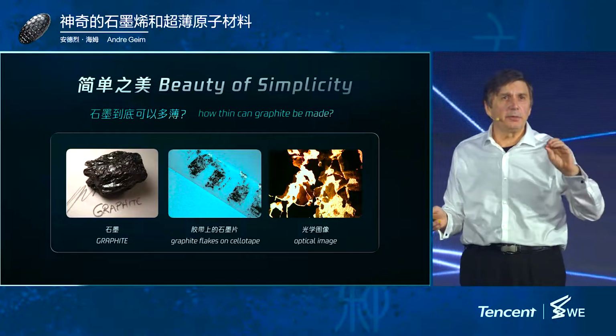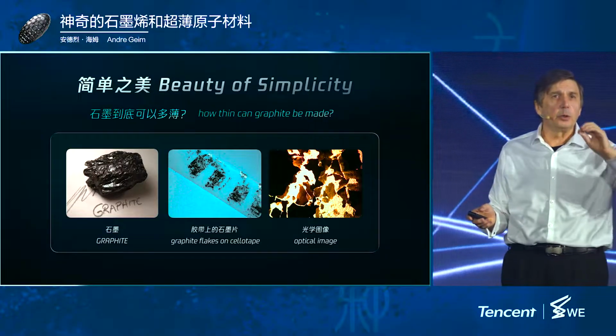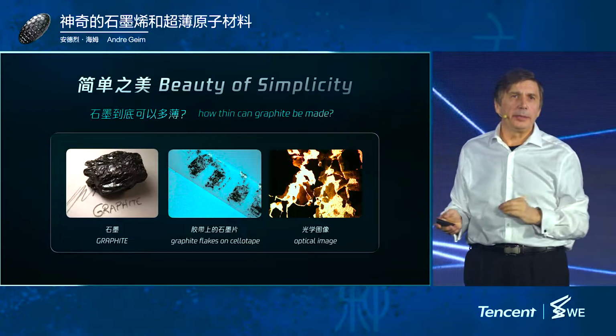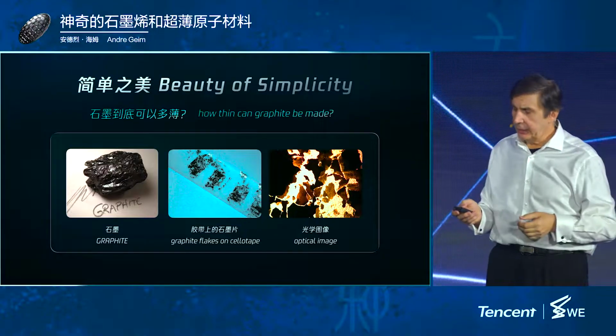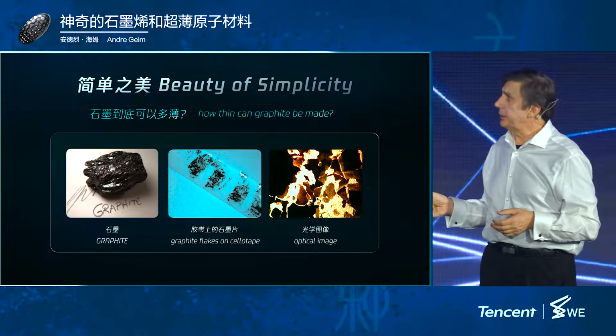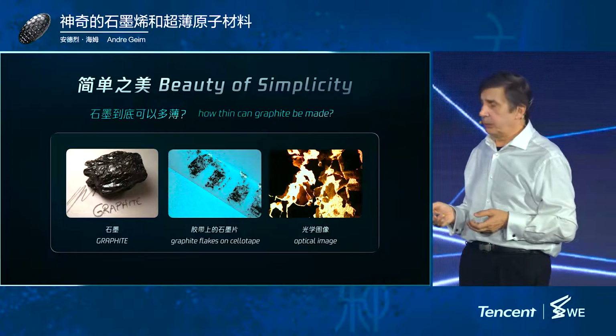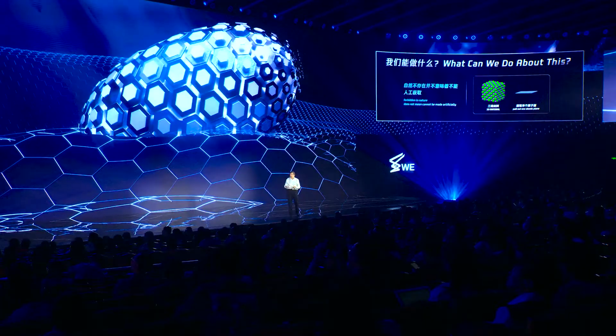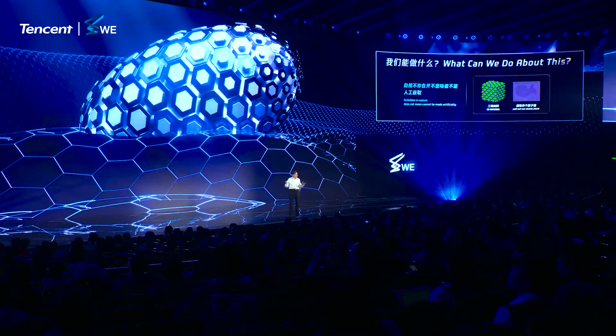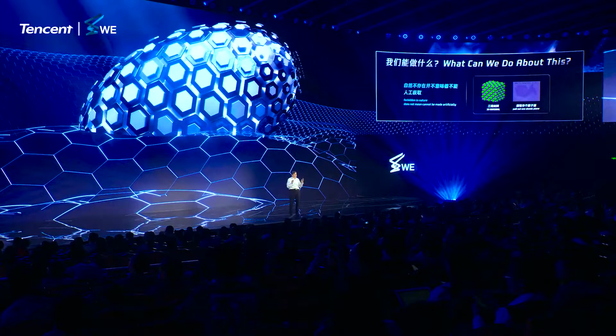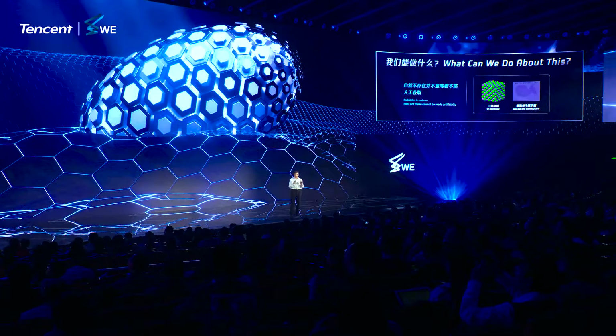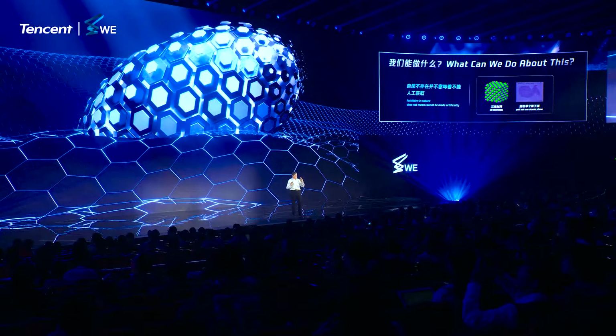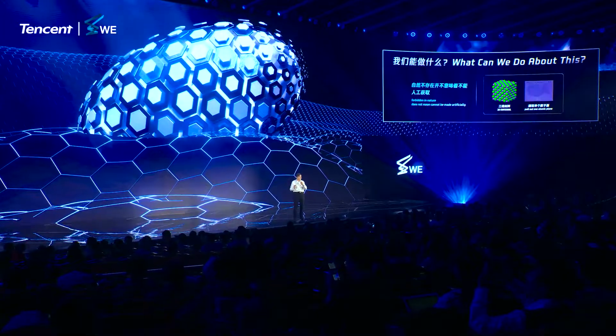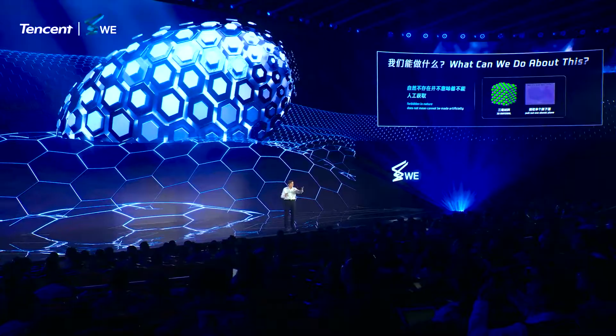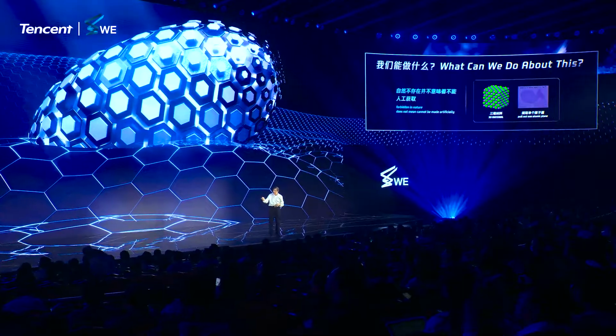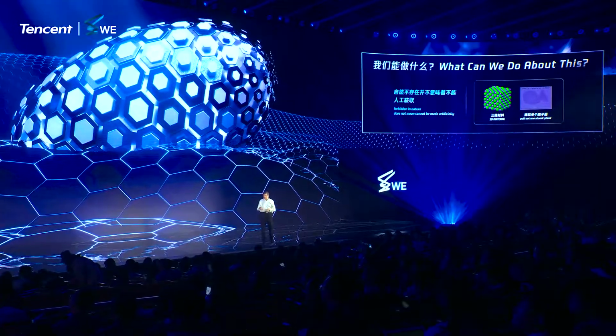We were looking for a thin film of graphite. The fact that it could be a few layers or 1 atomic layer thick came as a surprise for us and for colleagues around. So we essentially did this experiment of extracting an atomic plane, not by tweezers, but by scotch tape. And this is how graphene looked 20 years ago. It's a piece of crystal. It's a crystal structure without any defects. And it's only 1 atom thick, and you see it with the naked eye. Between me and you, there are billions and billions of atoms, and it's transparent. Here we see the one-atom crystal lattice.